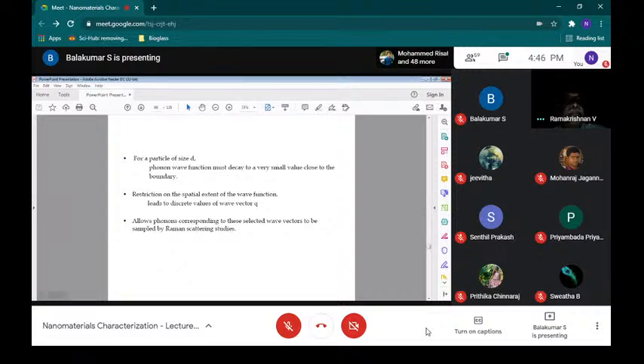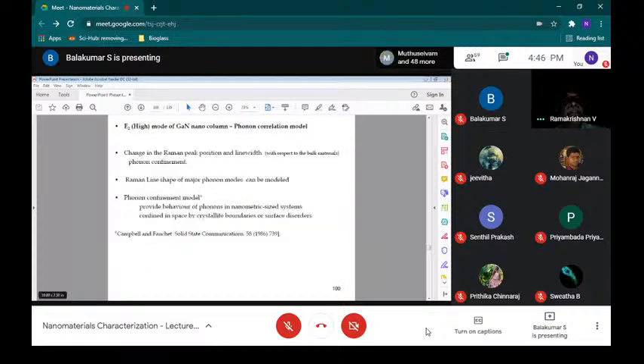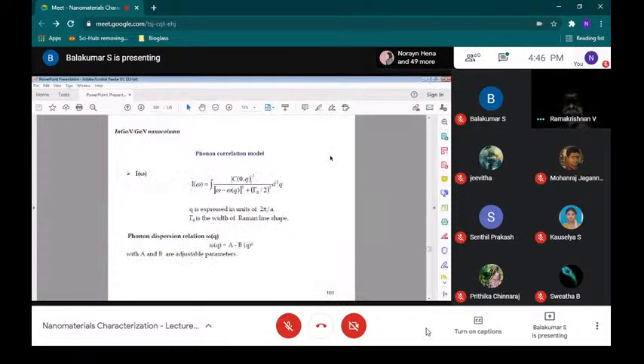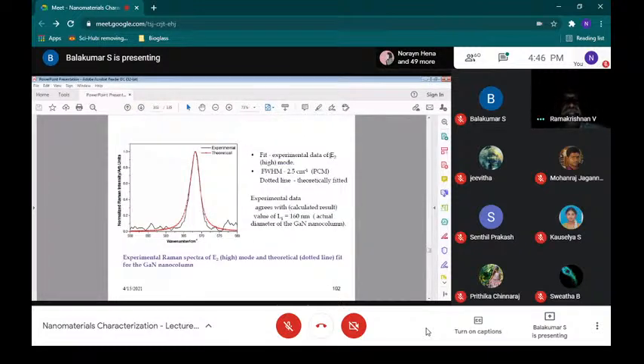So the phonon correlation model is applied for the E2 mode of gallium nitride. Okay, so this is a numeric. This is the expression. So based on the expression, the intensity plot is made. That is, the dark line is experimental, the red line is theoretical. So for the grain size, the D value, we try to fix it for a particular value of 160 nanometer.